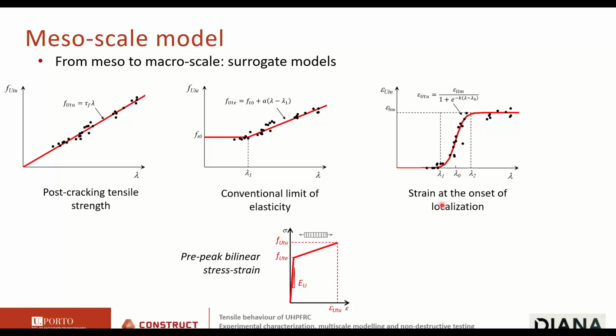So the good news is that we really don't need to use this meso-mechanical model, this meso-level model, in our finite element analysis. We can use much simpler surrogate models. What does this mean? We can derive very simple equations that give us the parameters that we need: the strain at onset of localization, the conventional limit of elasticity, the post-cracking tensile strength. All this can be obtained with simple functions, which of course can be or should be calibrated with the meso-mechanical model.